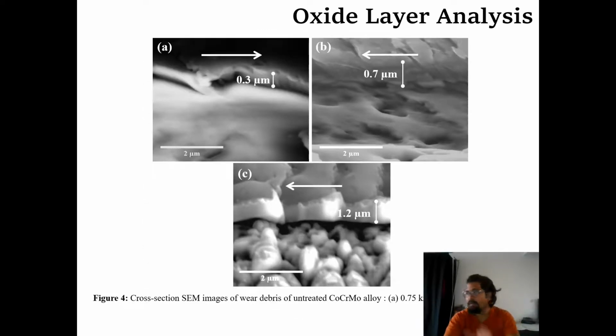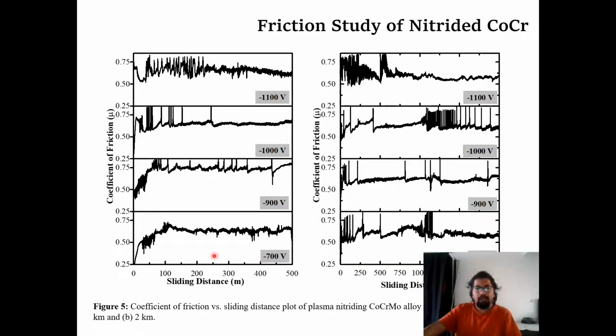layers were formed, and this defines that the CoCrMo alloy at some point starts making its own oxide-based protective layer, and these protective layers' thickness can vary from 0.3 micron to 1.2 micron, and here is the transformation of this oxide layer. So A is when it was 0.75 kilometer, B is when it was 1 kilometer, and C is when it was 2 kilometer.